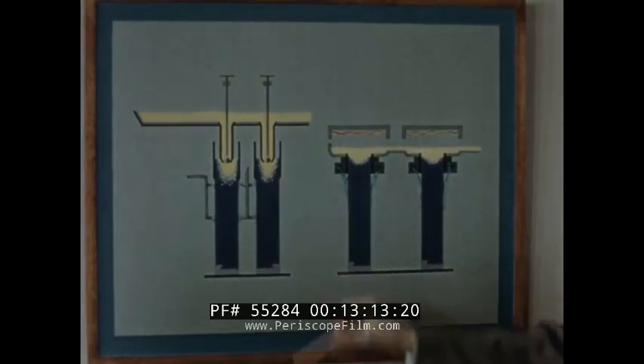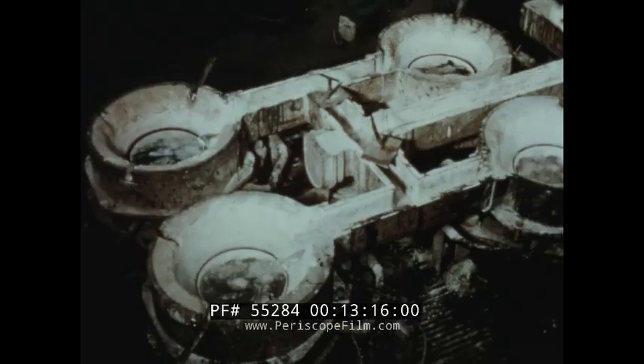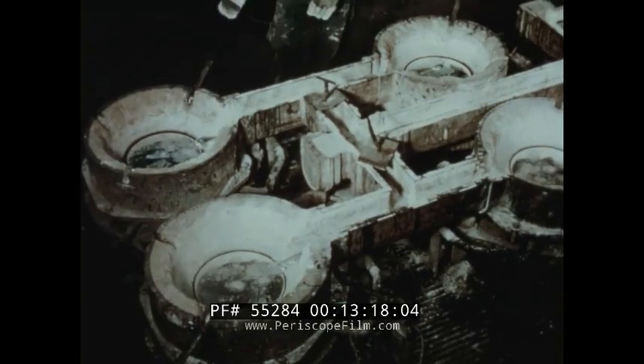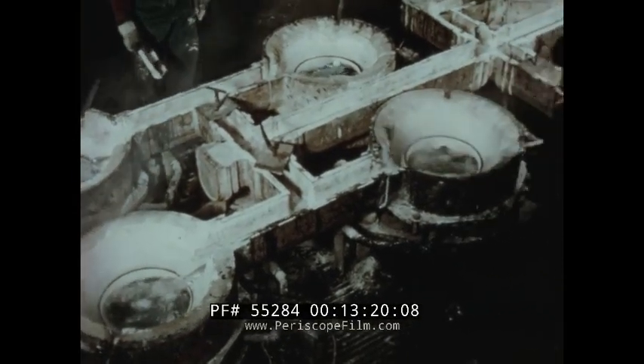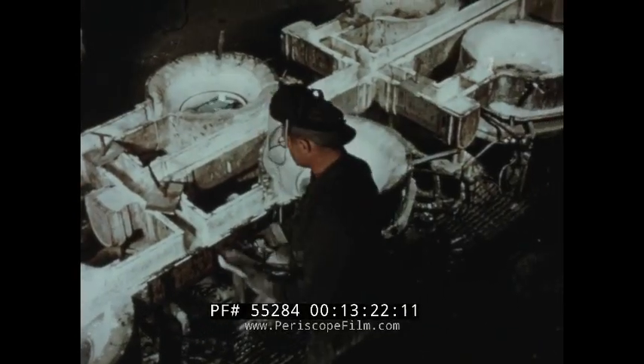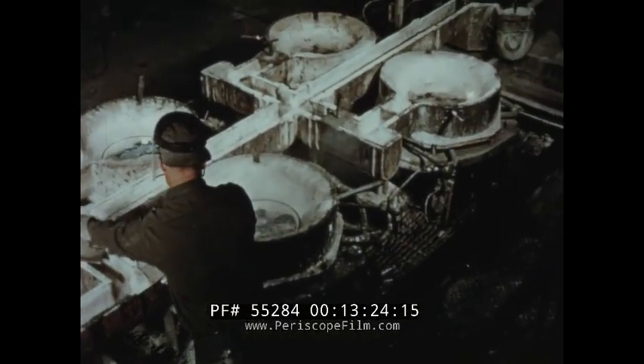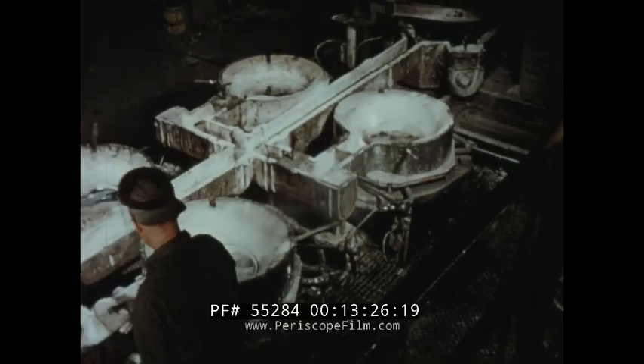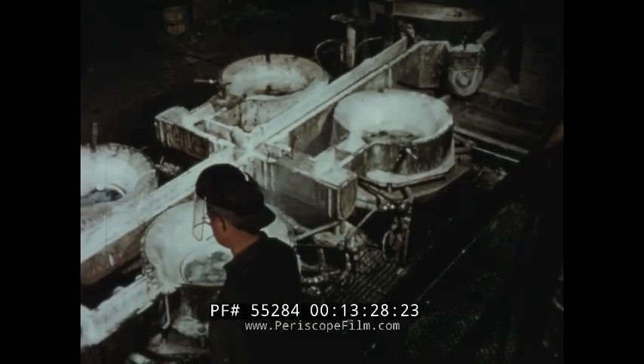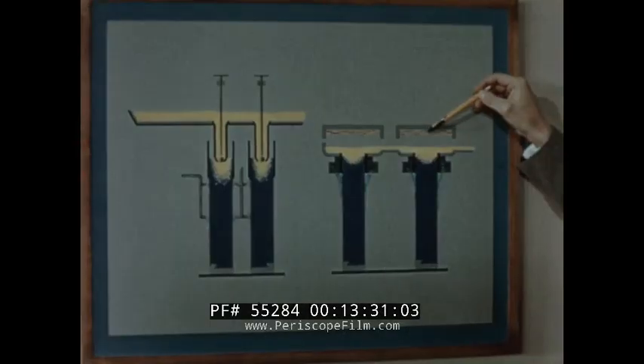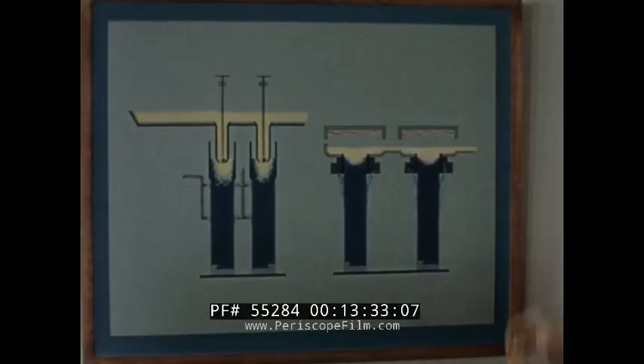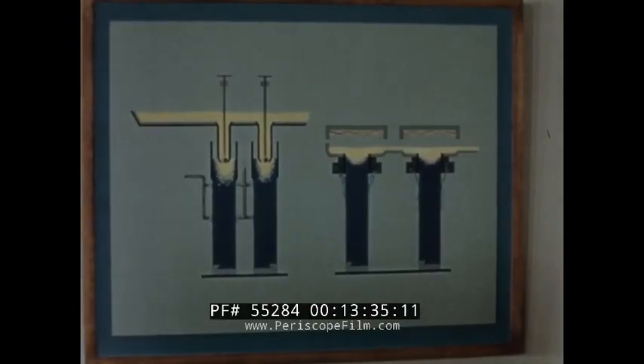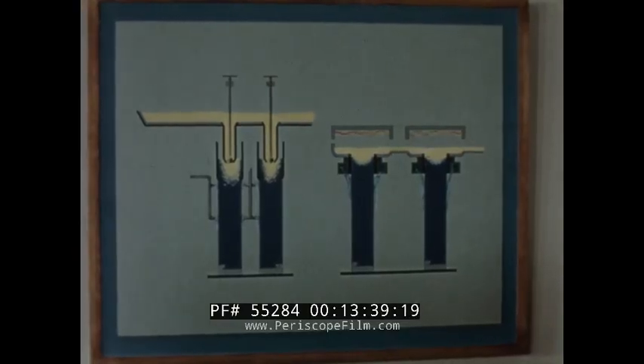At Messina, a somewhat similar method known as the liquid top process is used. In this liquid top process, the molds are made of graphite, and the tops of the molds are submerged in a pool of molten metal, kept at a constant temperature by heating units. For this method, it's not necessary to control the flow of metal into each individual mold, since they're all supplied from the pool or liquid top. The long ingots are later sawed into sizes suitable for fabrication.